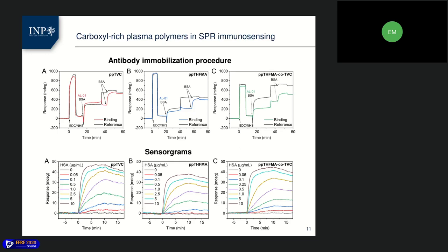During the immunotests, the performance of the TVC and the copolymer film-based sensors was very similar. The TFMA-based sensor had the smallest amount of antibody bonded to its surface and was worse in terms of sensitivity and level of response. Even though the TVC-based sensor had a slight drift and relatively noisy signal because of the non-uniformity of its thickness resulting from high volatility of this compound, the level of response towards the analyte was slightly larger than in the case of the copolymer-based sensor.